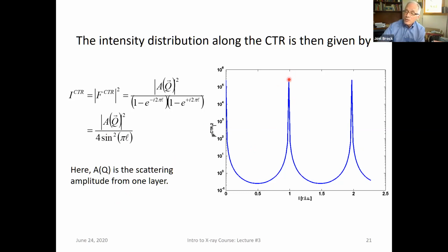When we get really close to the peak of the Bragg peak, you'll see that experimentally we can get the reflectivity of the crystal as 1, which means that every single X-ray is reflected, and the kinematic approximation breaks down. So right in the center here, there'll be a breakdown of our kinematic theory. That can be dealt with by the dynamical theory of diffraction.